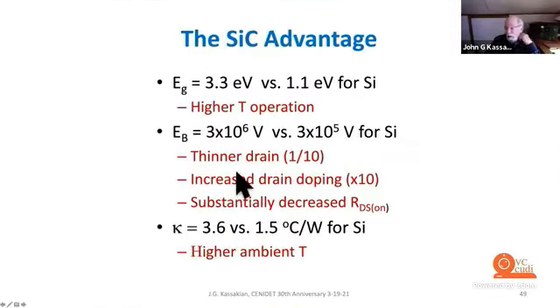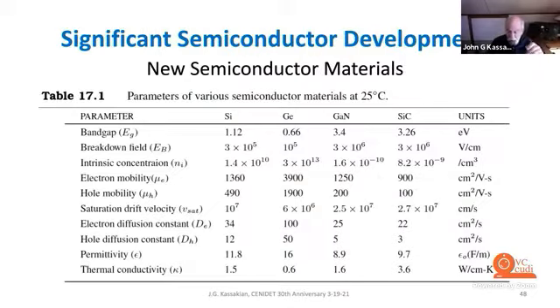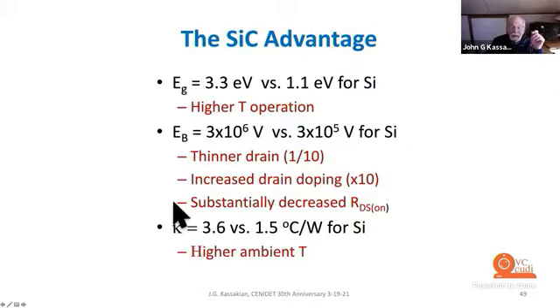We can also, if you think about this carefully, if we want to support the same voltage, we can increase the drain doping by a factor of 10. So the combination, thinner drain, factor of 10, increased doping, factor of 10, theoretically, we can decrease the on-state resistance by a factor of 100. Now that's in theory. Of course, there are other elements to the on-state drop that aren't included here. But what it does show is that silicon carbide for a power device has immeasurable benefits.